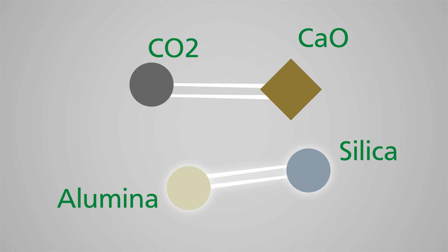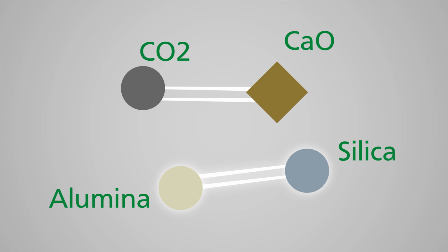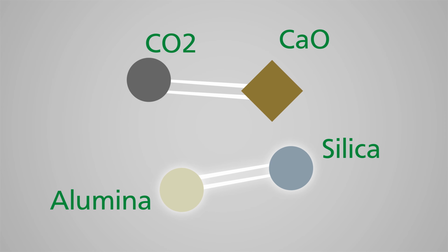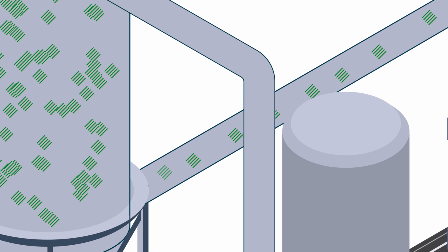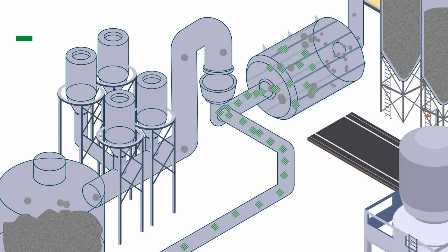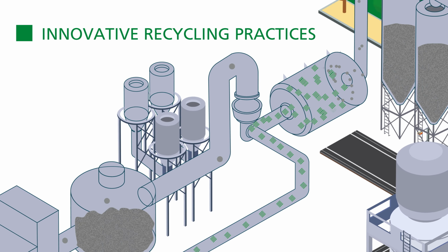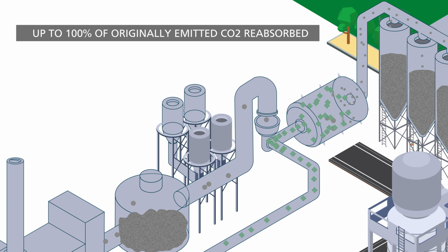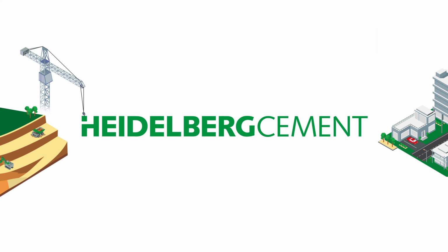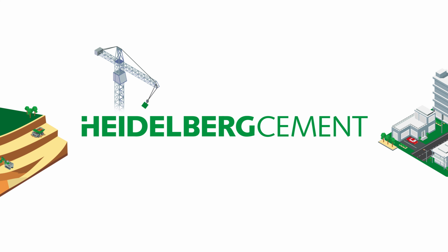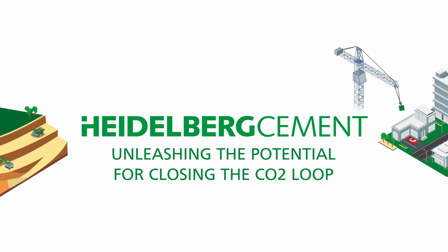The silica and alumina, also present in the RCP, form a pozzolanic, highly reactive gel. This recarbonated, recycled concrete paste can be utilised as clinker replacement and can also replace the supplementary cementitious materials. The result? Cements with an even lower CO2 footprint. On its path to carbon neutrality, HeidelbergCement not only supports the circular economy through efficient use of resources and co-processing waste material, but also through recycling concrete.